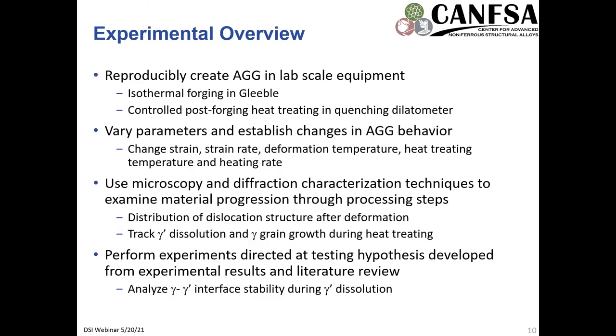And so, an experimental overview of what we did and why. First, we wanted to be able to reproducibly create abnormal grain growth in lab scale equipment. We utilized the Gleeble for precise time, temperature, and deformation control during isothermal forging. And we wanted to control the post-deformation heat treatment, the supersolvus heat treatment, in the quenched dilatometer to try to get precise results and consistency.